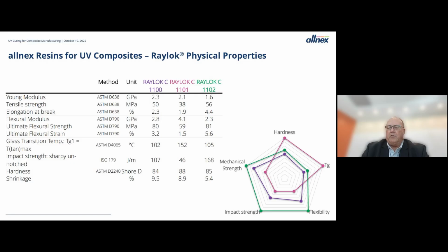And the little radar plot there shows how the three materials compare to each other. So you have the purple is the 1100, and it's just got a very basic formulation, does everything pretty well without any one aspect being outstanding. The 1101, the high TG material, has high hardness, high TG, and the 1102 is a material with really excellent mechanical strength, impact strength, and some flexibility. So depending on what your application is, these are materials you can start with. If they're sufficient, that's wonderful. If not, we have the formulation expertise to create something that is exactly what you need.